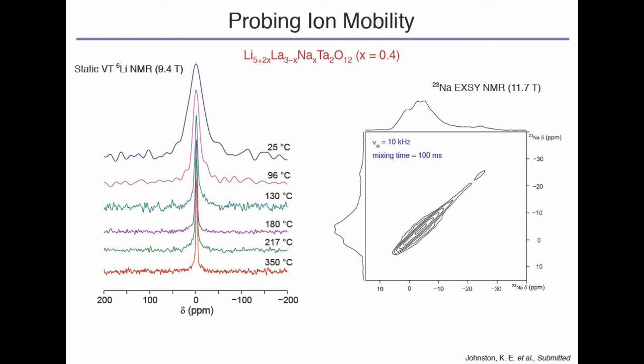Now, I said we wanted to know where the sodium is, but we also want to know if the sodium is contributing in any way to the ionic conductivity of this material, because sodium itself is quite small. It's similar to lithium. It could also be moving through the structure and contributing to that conductivity. So what we can do is an experiment known as an EXSY experiment, or exchange experiment. Imagine you have two sodium sites next to one another. If they want to switch and exchange places, they can do that, and this is how we can probe it using an EXSY experiment.